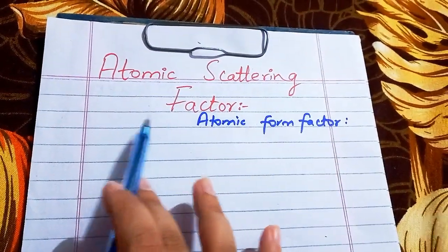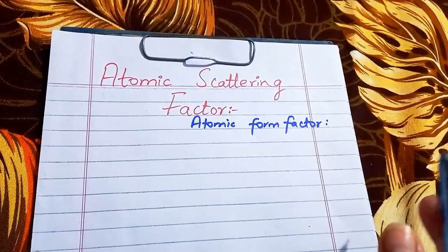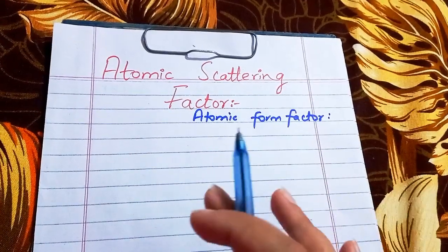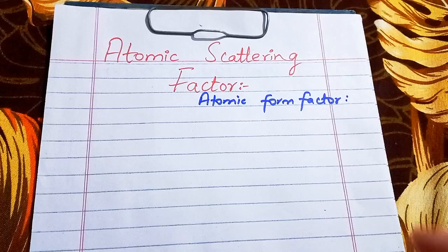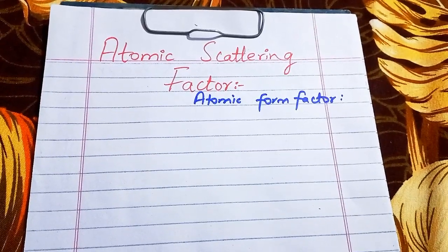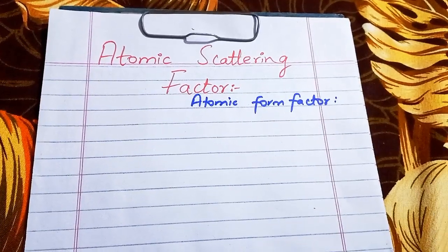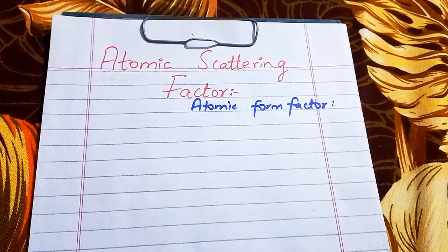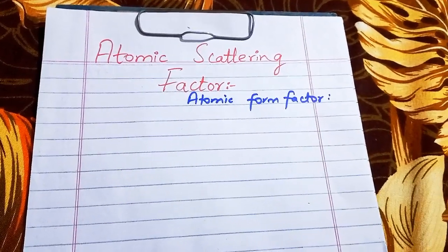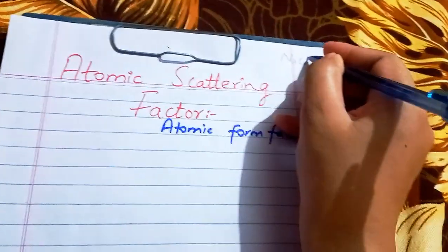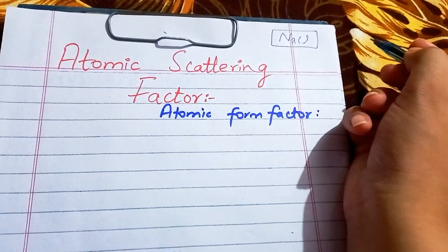Greater the atomic scattering factor, greater the ability of an atom to scatter the X-ray beam. This is the reason the atoms with the higher atomic number have a higher atomic scattering factor. This is because their electronic cloud is huge and they are capable of scattering the X-ray beam considerably as compared to those atoms that have comparatively less atomic number. For example, if you consider a NaCl crystal, it is a good example of a crystal that has two kinds of atoms in it.